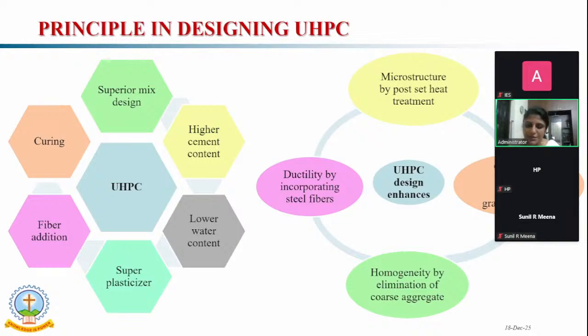We have conducted many parametric studies by varying all the constituents to develop the UHPC, and finally we have arrived at an optimized granular mixture. Then we can enhance the homogeneity by eliminating coarse aggregate. Also, we can reduce the weak section in the ITZ zone. Then we can enhance the ductility behavior by incorporating steel fibers. By adding the steel fibers, what actually happens is that it will bridge the